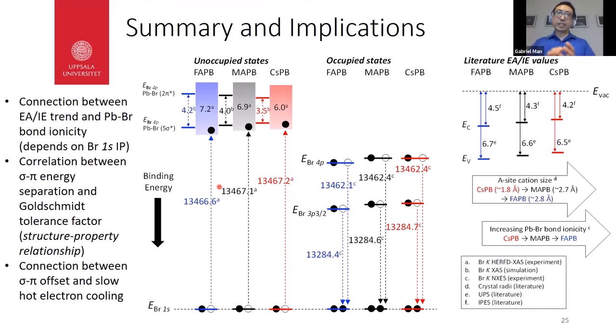In this slide, I will bring together all of the different measurements to see what sort of trends we can extract. First we look at the unoccupied states over here. This is the absorption onset trend, where we see an increasing trend as the A-site cation gets a bit smaller in the case of cesium. We see a similar trend with the study of the occupied states relative to the bromine 1s core level. What's interesting is that there seems to be a correlation between our findings over here and electron affinity and ionization energy values reported in the literature. There seems to be this sort of step function as well. So we think there's a connection. It depends on the bromine 1s ionization potential, which I can only speculate a little bit about and won't talk too much about. But yeah, there seems to be a connection.